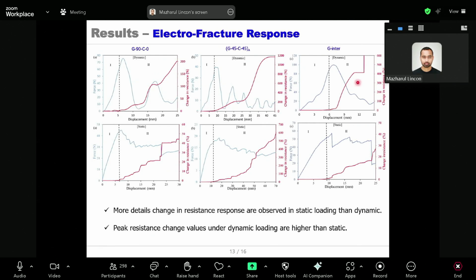The first three are dynamic loading conditions, and the last three are static loading conditions of the same specimen. In every specimen, either dynamic or static, you can see after the black dotted line, change in resistance increases gradually, because after that point the specimen starts breaking and its change in resistance actually changes. From these changes we can learn that some damage happens in the specimen. That's the main concept of doing this electrofracture response.